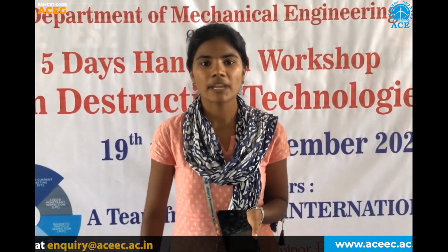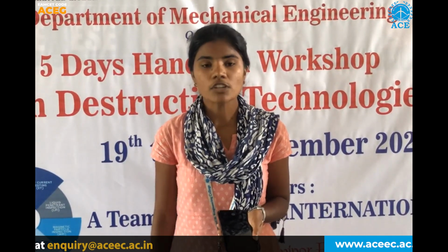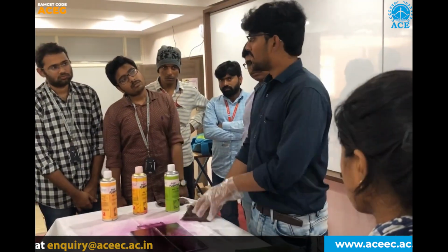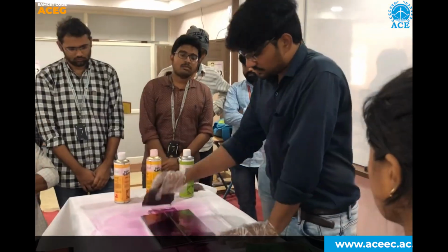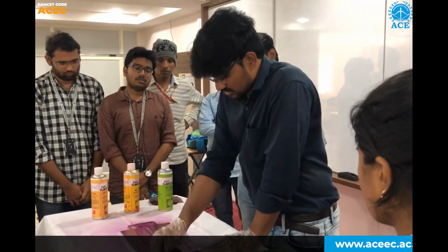Third process is dwell time. After applying the penetrant, a minimum of 10 minutes should be given to allow the penetrant into the openings of the surfaces. Next process is removing the extra penetrant. It is removed with the help of a cloth in any one direction.